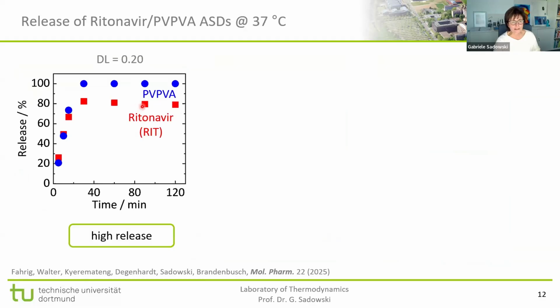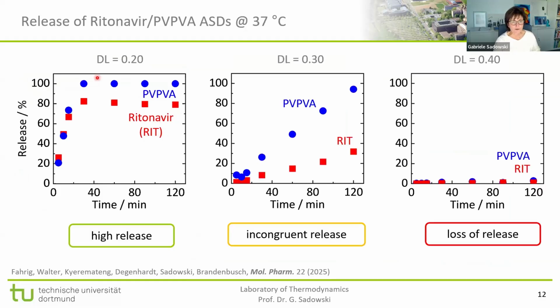So we have ritonavir, that was the molecule on the previous slide, and PVPVA, and it's exactly the same situation as before. The higher the drug load, the smaller the release of the API, in this case ritonavir, and then at 40% drug load, and this is really a reasonable number, which is quite often used for pharmaceutical products, none of the components releases anymore.